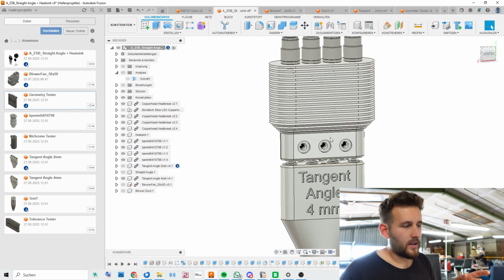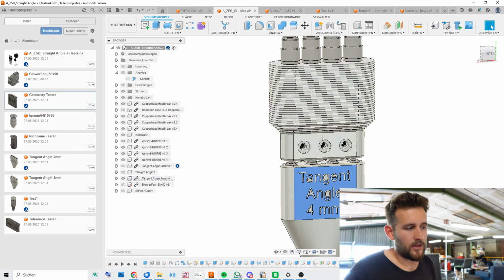When testing yesterday, I also had a thermistor up here in the cold end section to monitor how much of that heat travels upwards into that area. Of course, especially with PLA, with its glass transition temperature somewhere above 50 degrees, we have to make sure that this stays cool enough so the plastic isn't getting into a somewhat fluid state. We lose all our control over that puddle at that moment and it will just clog up. Even when this hot end was at 250 degrees with a blower fan up here, we didn't exceed 48, 49 degrees. So I think with a bit of tweaking we get that even a few degrees lower. Right now it is also 30 degrees here in the company. So I guess we can figure that out.